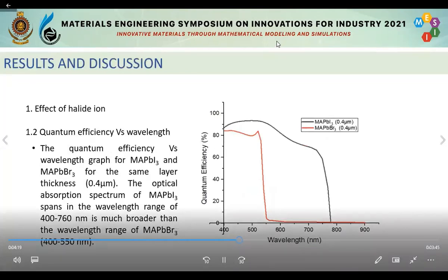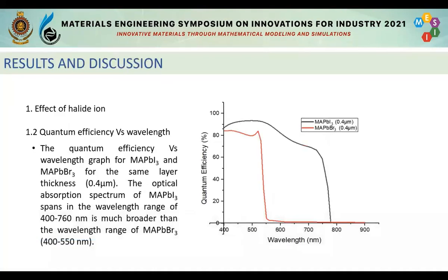This figure shows the quantum efficiency versus wavelength graph for methyl ammonium lead iodide and methyl ammonium lead bromide for the same layer thickness. The efficiency of the methyl ammonium lead iodide solar cell is higher than the methyl ammonium lead bromide solar cell because the optical absorption spectrum of methyl ammonium lead iodide, spanning the wavelength range of 400 to 760 nanometers, is much broader than the wavelength range of methyl ammonium lead bromide.